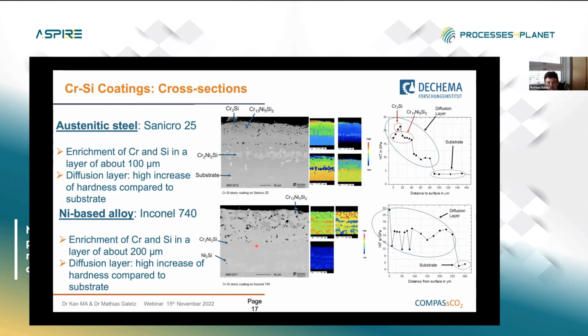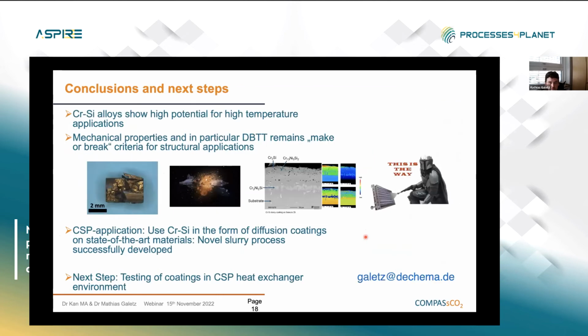And you have to keep in mind that this was cooled down from an extremely high temperature of above 1100 and doesn't form cracks. So the CTE, the thermal expansion coefficient, which is usually of concern for those systems, is not an issue. And this shows that probably also at the application temperature of around 800 degrees, it should not crack. Okay, the next slide, please.